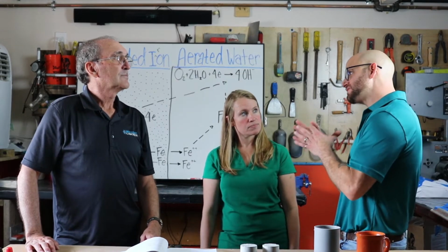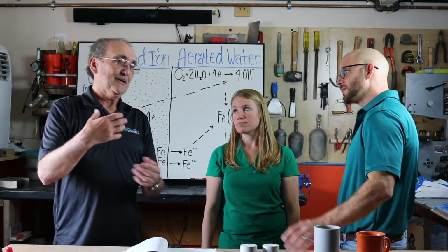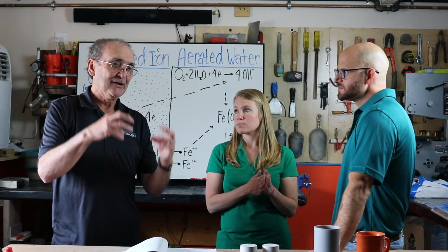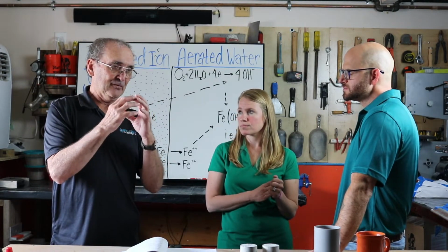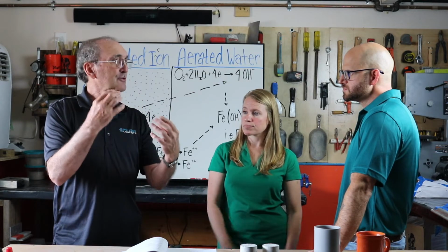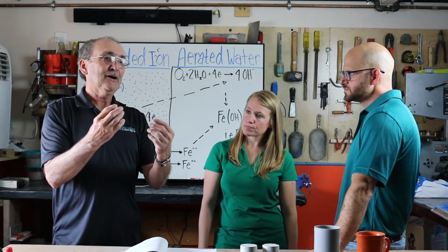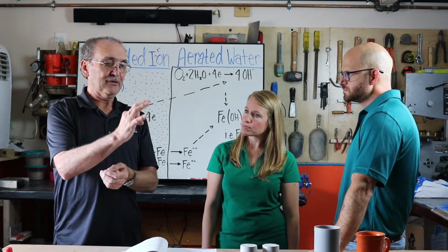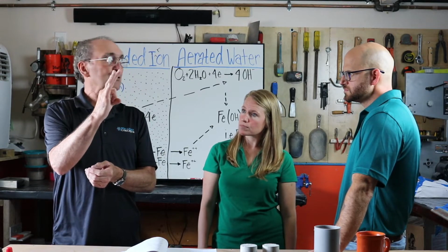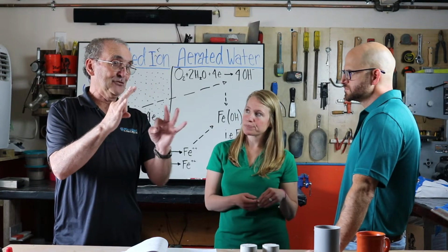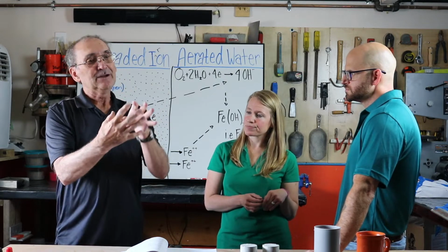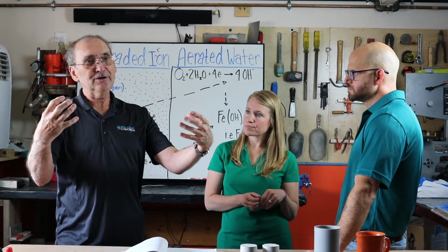What happens to that steel? Yeah, it's both bad news. The corrosion, the rust itself causes an increase in volume. But by rusting, the actual usable area of the steel is less. So you have shrinking, less usable steel, that's bad. And we have rust, which is causing an increase in volume, that's bad.